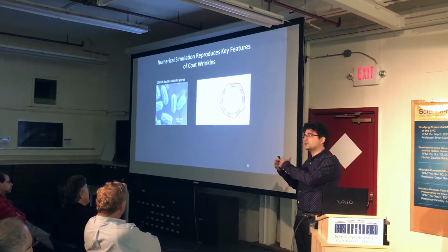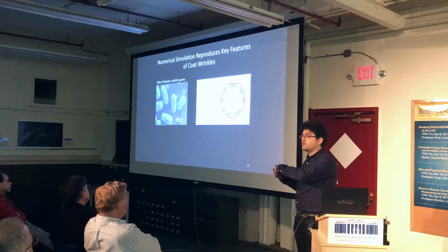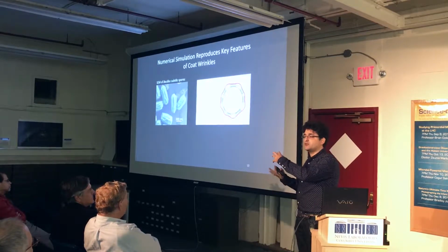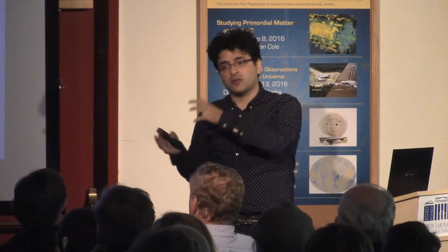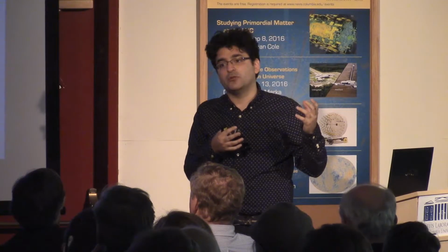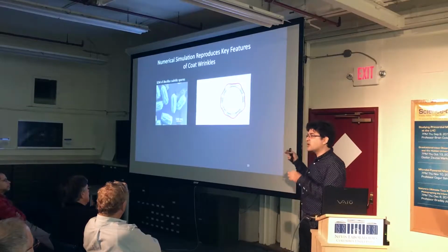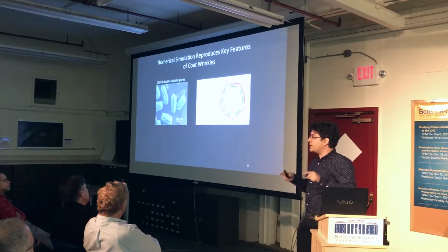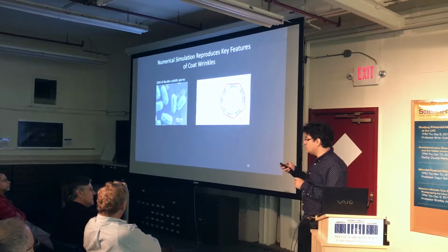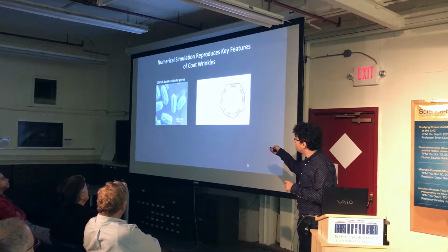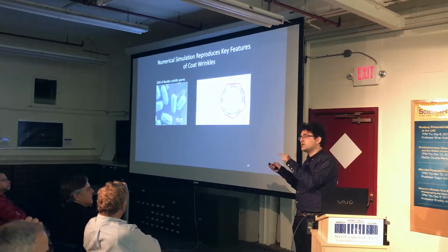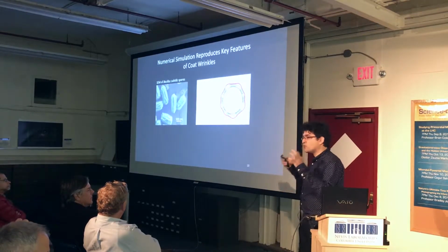And as the spore goes through its life, every day, for example, humidity will change, and the spore will expand and shrink. These wrinkles will help the spore accommodate that size change. Moisture can create damage, right? If you have wooden furniture, when you put it in a dry environment and a humid environment, you can form cracks. For this organism, that would be damaging because it has genetic material that it needs to protect. And this coat layer, because it's accordion-like, gains flexibility. It uses a really tough and rigid material, but because of these folds and wrinkles, it becomes more flexible.